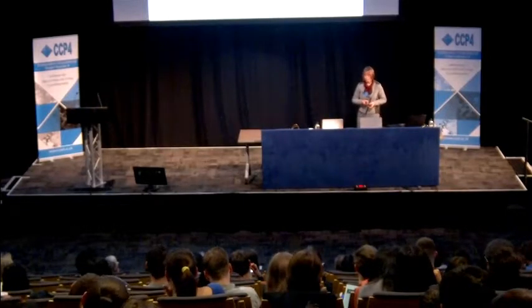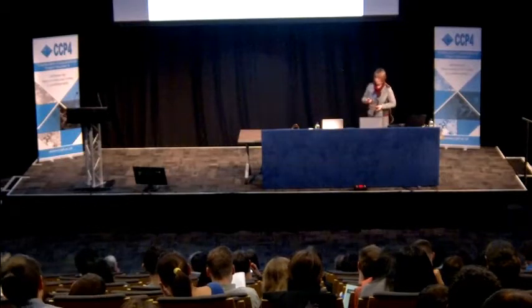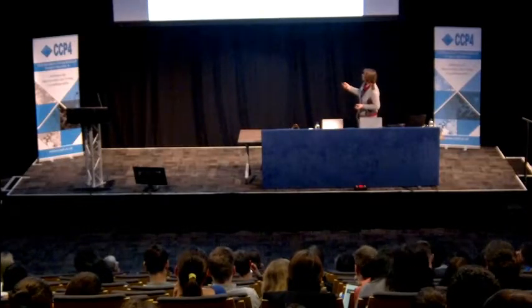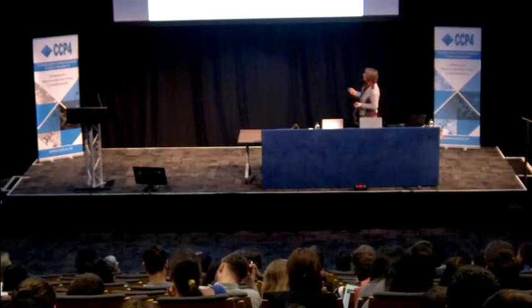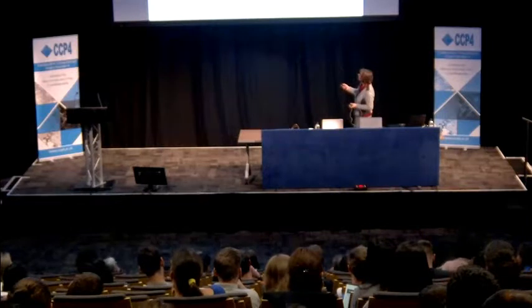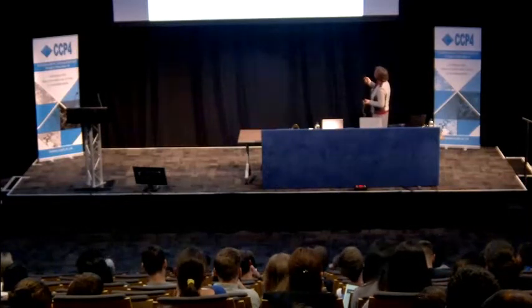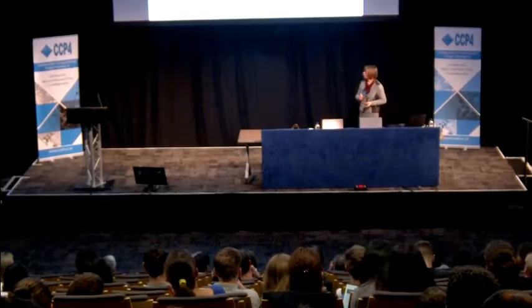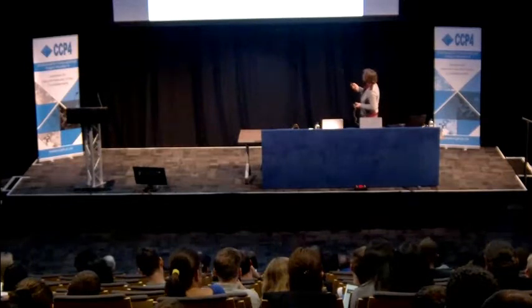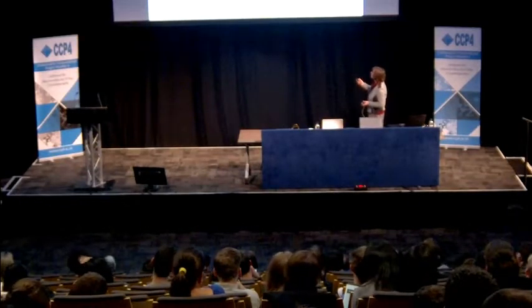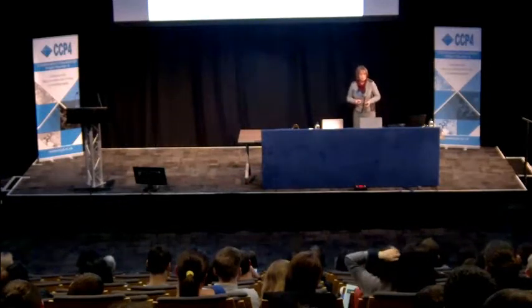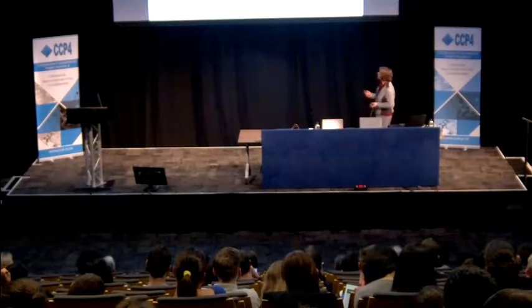The next step is the integration. Coming back to the three types of reflections and thinking of integration boxes: using the orientation matrix of the blue domain, we would integrate the sum of both intensities — the sum of the red and blue intensity. For non-overlapped reflections, we would just have the intensity of the blue reflection. That would be identical to merohedral twinning and to a normal single crystal. But for the partial overlaps, we have the problem that we get the whole intensity for the blue domain but only part of the intensity of the red domain, and we don't know the degree of overlap.